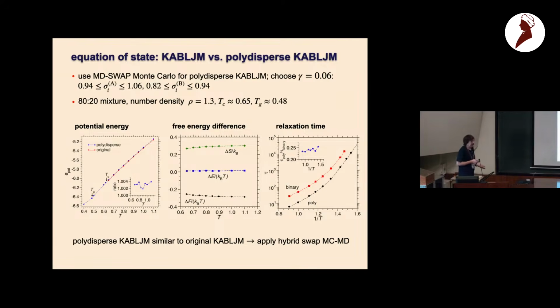Now we can compare the polydisperse variant with the original binary system, and this is first of all the potential energy as a function of temperature. Of course we get to much lower states in equilibrium here with the polydisperse version, shown in blue - these are the blue data points. We see that the potential energy per particle is very similar to the original binary system, so if one takes the ratio in this area here, it's slightly above 1.